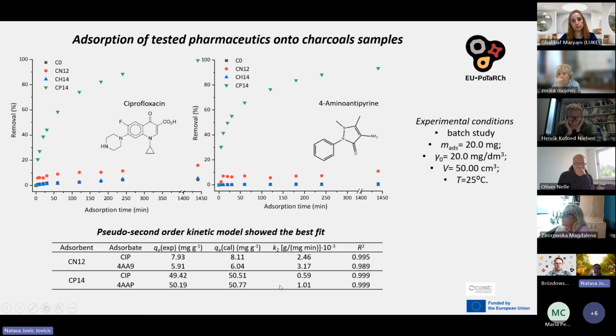At the bottom, in this table, we have the kinetic results. The data fit best with the pseudo-second-order kinetic model, suggesting, according to some authors, that chemisorption could be a dominant mechanism. We see that adsorption capacity for the CN sample is very low, while the CP samples show much higher experimental and calculated values, around 50 milligrams per gram for both pharmaceuticals. These findings highlight again that the activation process by phosphoric acid led to the production of the most effective adsorbent for removing the pharmaceuticals that we tested.